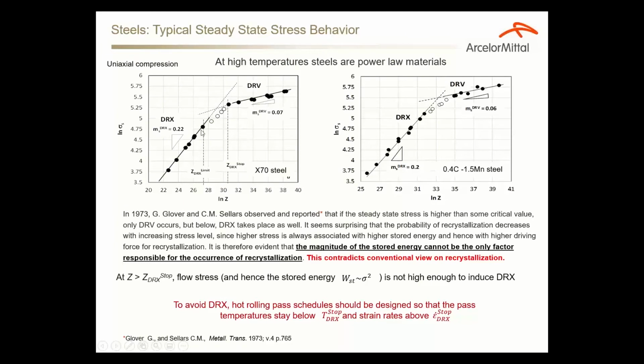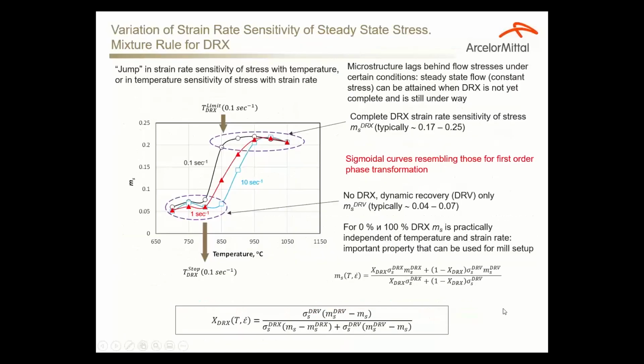Based on our experience, I can tell you that the majority of steels we're dealing with exhibit this kind of behavior. It's something very confusing, but this type of behavior was actually reported a long time ago, 50 years ago. Interestingly enough, the strain rate sensitivity of stress or temperature sensitivity of stress changes non-monotonously. For the dynamic recrystallization range, it does not depend on temperature or strain rate, and is pretty much constant. Same when dynamic recrystallization is absent.